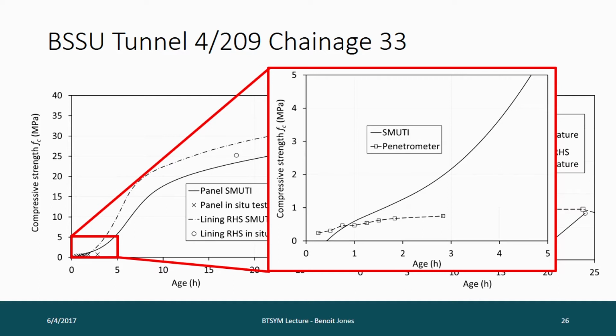And even if it's got zero strength, it will read something because of the friction. You're trying to push a needle into a granular material that's quite compact. So I think the penetrometer might be over-reading. But also, you see later on the effect of the penetrometer reaching its maximum limit. You can't really take a reading more than 0.7, 0.8. And just because we were trying to take as many readings as possible, we carried on with it.